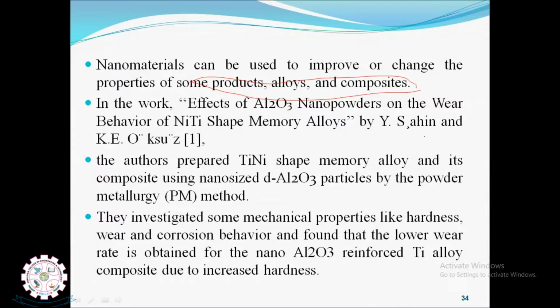by Y. Şahin and K.E. Öksüz, they published the paper on the effect of aluminum oxide nanopowder on the wear behavior of nickel titanium shape memory alloys. They prepared a nickel titanium based shape memory alloy, and developed the composite material using Al2O3, aluminum oxide nanoparticles, by powder metallurgy method. They investigated mechanical properties like hardness, wear and corrosion behavior, and found that a lower wear rate is obtained when they added the nanomaterial Al2O3.